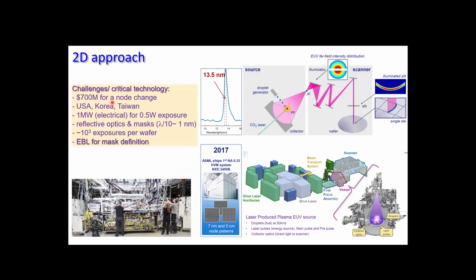Here are some numbers. If we change the node from, let's say, 5 to 4 nanometers lithography, we should invest a huge amount of money. Only 3 countries, and probably Japan should also be added to this list, can have this technology. In terms of efficiency, from the wall you should use 1 megawatt of electrical power to reach 0.5 watt on the wafer when you are exposing your resist. You need many exposures when you are fabricating actual devices. Also, electron beam lithography should be used to define the mask which you are projecting on the wafer. So it's very, very complicated.